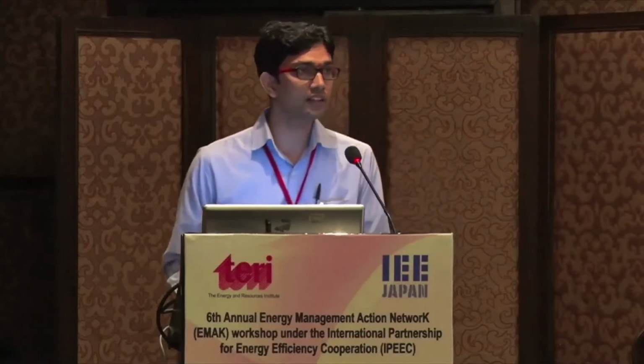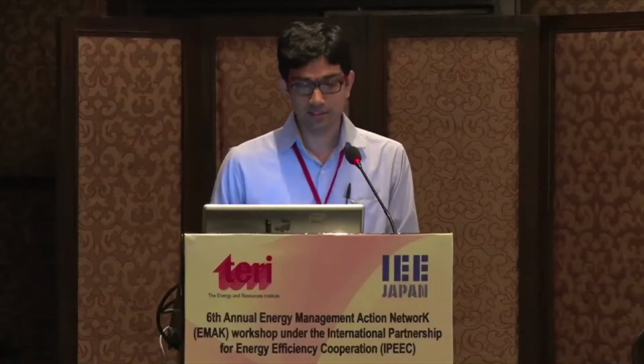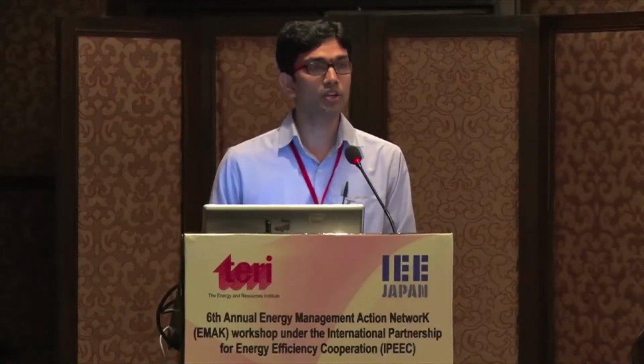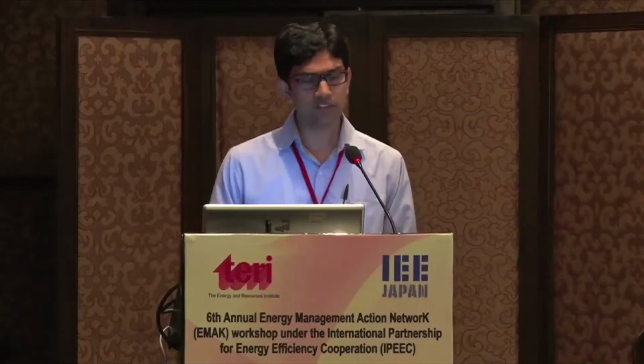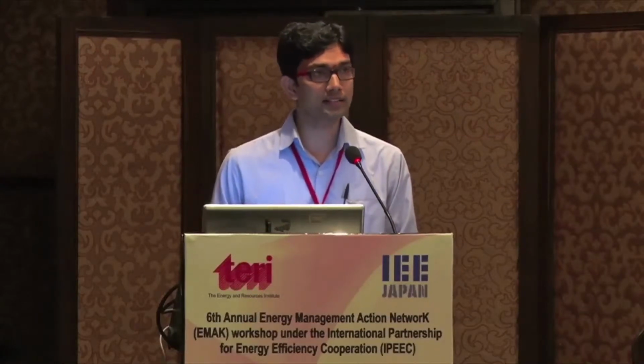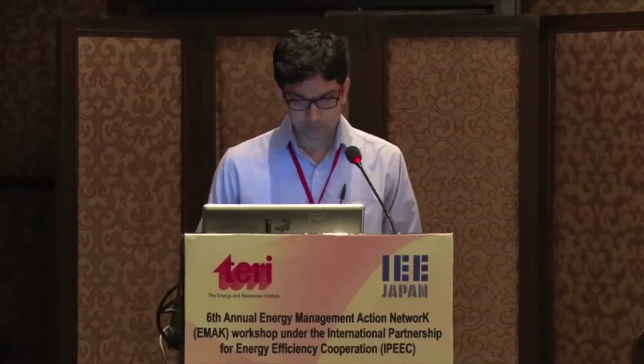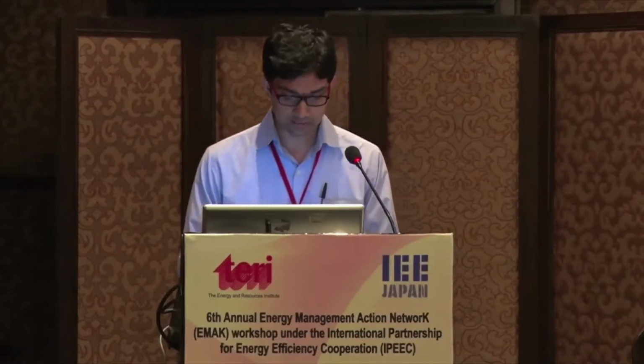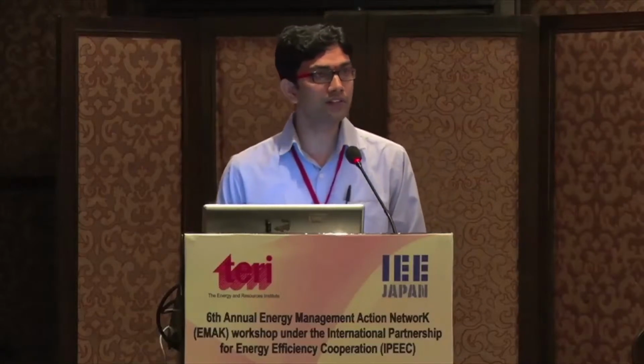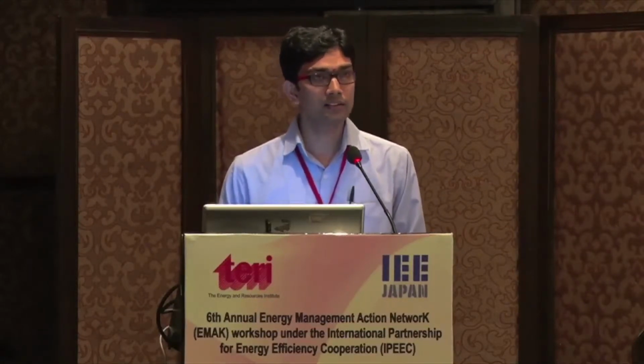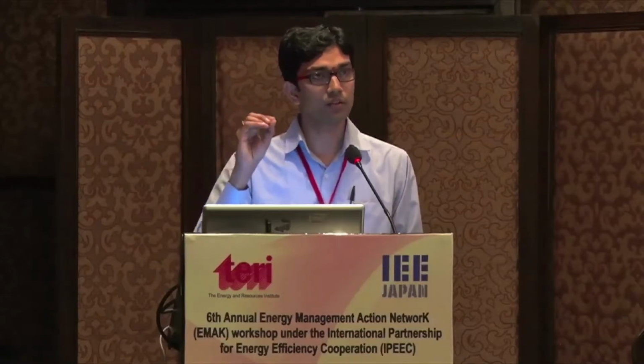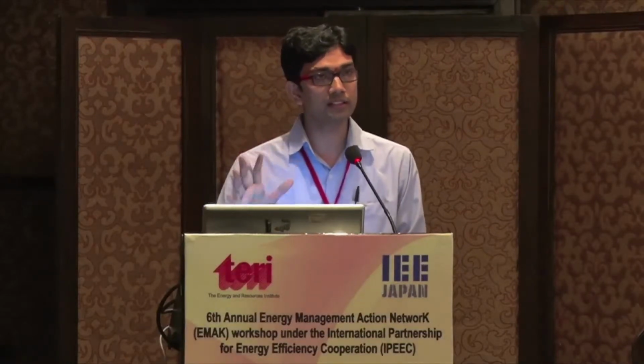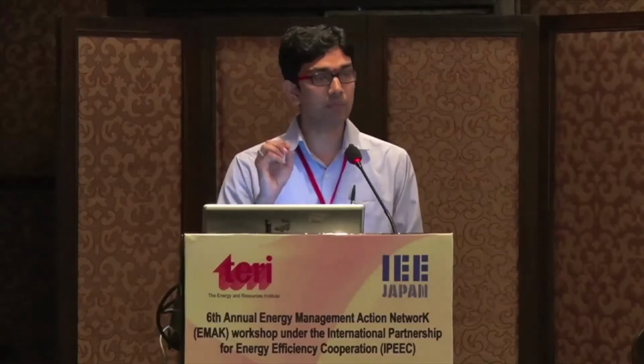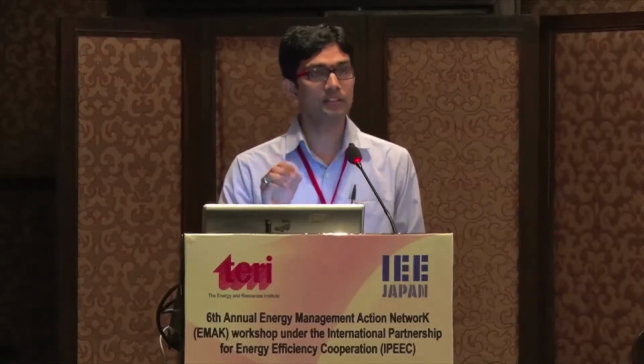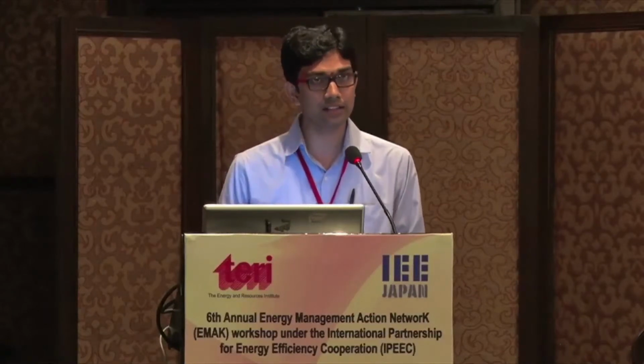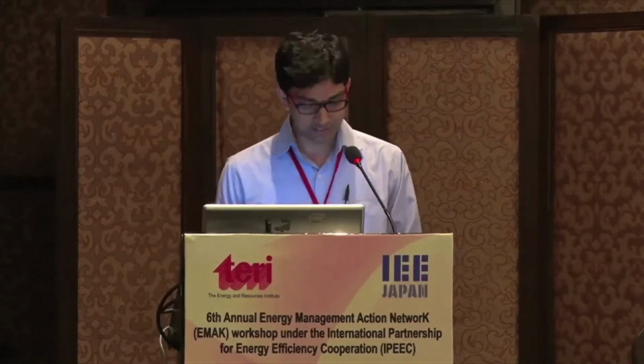If you look at the forging furnace and the fuel mix in Faridabad, 58%, the majority of the furnace users, use PNG or piped natural gas as fuel in their furnace, followed by furnace oil at 30%. And here we are talking about reheating furnaces, a box kind of structure, where furnace oil or PNG is pumped into the furnace with fresh air at ambient temperature, and the furnace is to be maintained at 1100 degrees centigrade on a continuous basis.